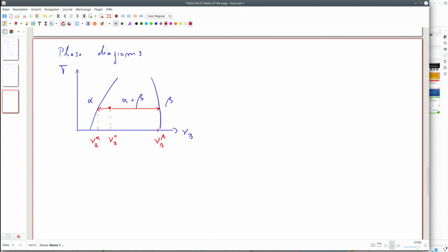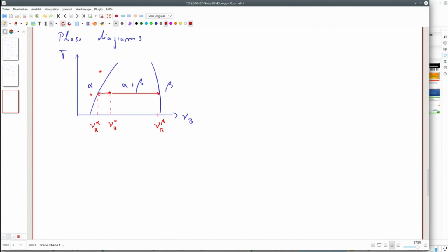And of course I could do this canonical Monte Carlo simulation starting here and checking which concentration forms here and here. Does it unmix or does it stay here? I mean, if I start here, it stays homogeneous. If I take a higher temperature, it is still homogeneous here, and so on. But this is quite time-consuming and tedious. Yeah? And there is a much easier way. This is kind of a transformation of ensembles.